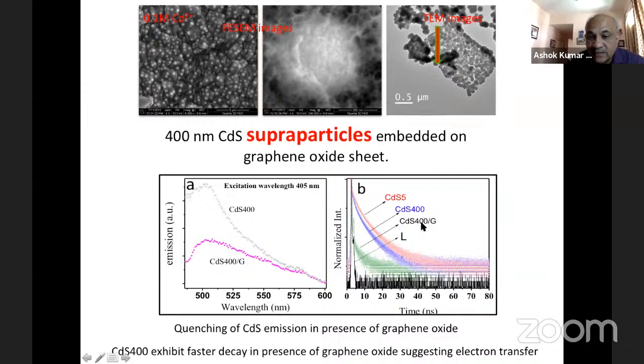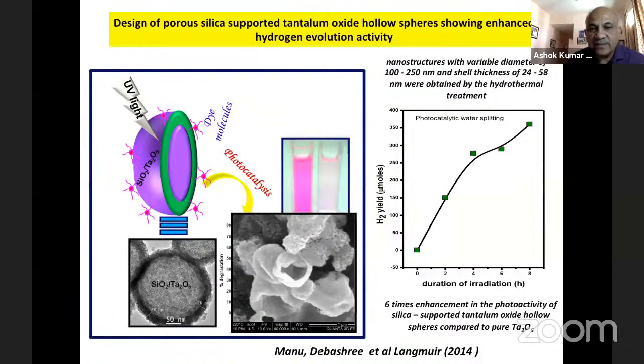So the CdS 400 in the presence of graphene oxide, if you look at the time resolved studies, you see it is a much faster decay compared to the pure cadmium sulfide supraparticle, the blue plot, or the pure cadmium sulfide small nanoparticles. Both of them have much longer decay. And so basically the electron can be moved away from the site when you have this graphene oxide substrate.